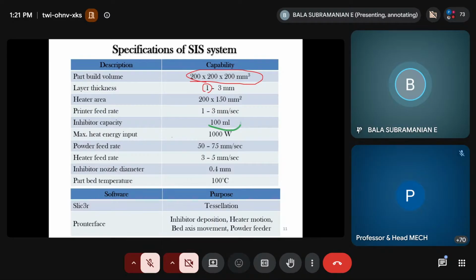So initially the powder layers were deposited. Now the inhibitor, so you can see a syringe, simple syringe, and it is now delivering the inhibitor. Okay, so it is a very cost-effective process. We have used whatever is available at low cost. So now this inhibitor has defined the part periphery, and the second motion, as I mentioned, the heater will come into play.